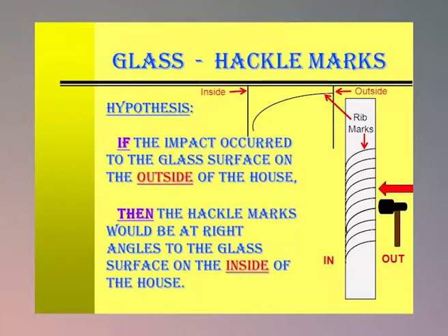Then comes the hackle markings. Hackle markings are found in that area on the fractured surface where there has been relatively high stress. These markings actually consist of ridges which are running in the direction of fracture propagation and are at right angles to any rib markings which may be internal. They are most prevalent when the fractured surface runs at an angle of 45 degrees to a pre-existing free surface. Thus, hackle markings are a definite indication of the direction of propagation.